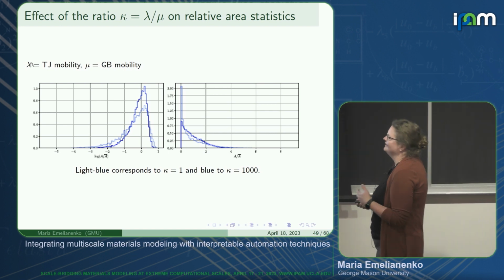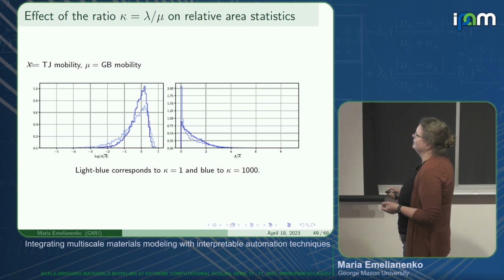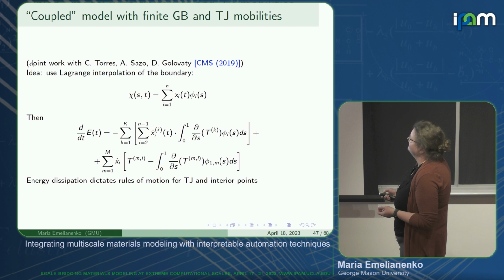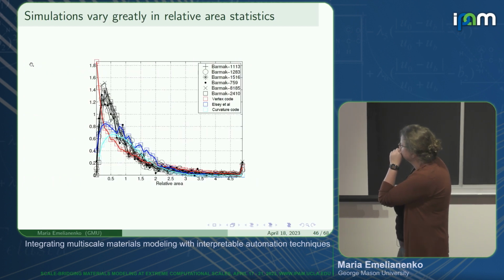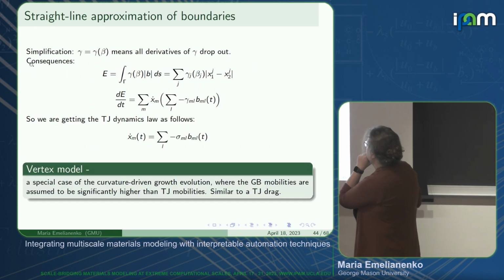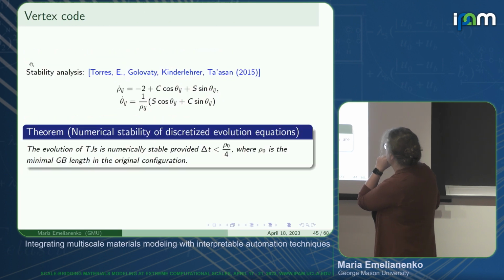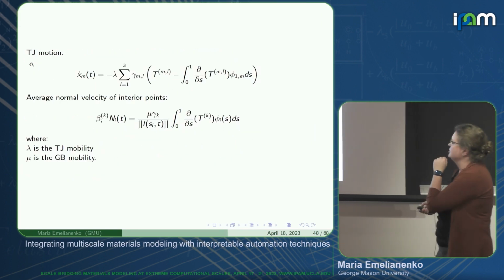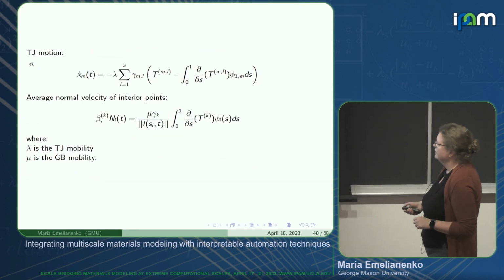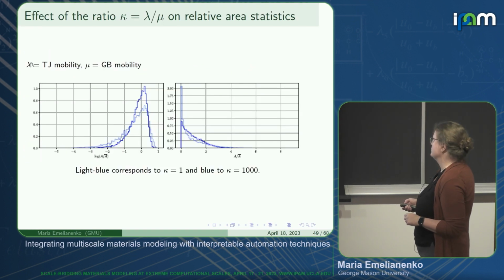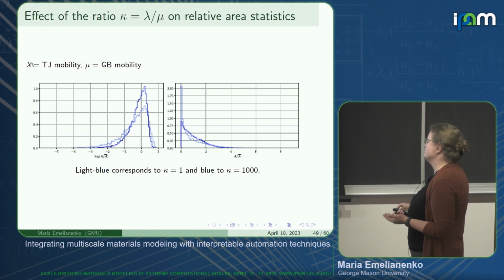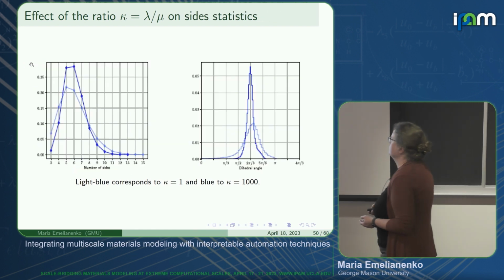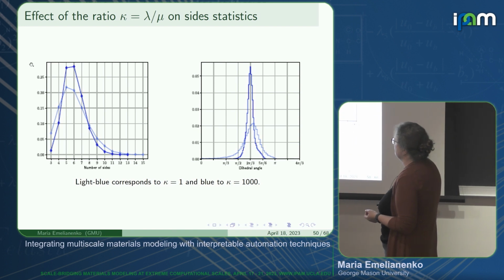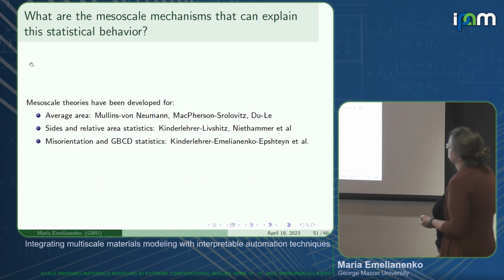So if you have 1, then they're equal. But if you have kappa equal to 1,000, then basically that would mean the triple junction drag. So this lambda dominates compared to the grain boundary. And you can change the shape of these distributions, and you can match it with the predictions of the experiment. But all of this is to say that